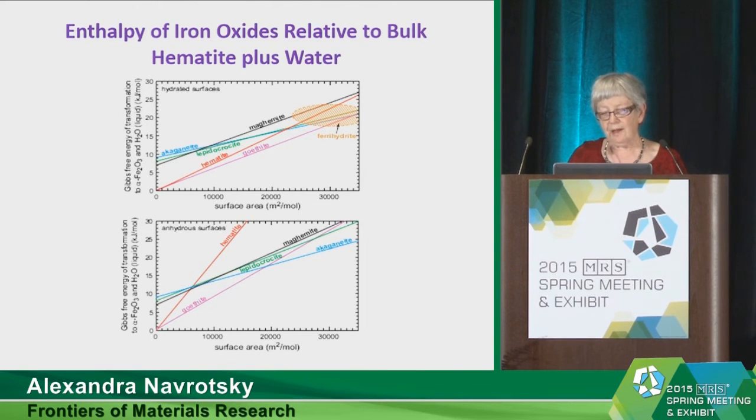If we look at the upper curve, at the upper diagram, because these things always are hydrated, correcting for the water adsorption enthalpy to anhydrous materials is probably not the real world, except perhaps maybe in space. What we see is that for large particles, one has a significant difference in the enthalpy and also in the free energy between polymorphs. But for small particles, because the ones that are metastable in the bulk have lower surface energies, they all become competitive.